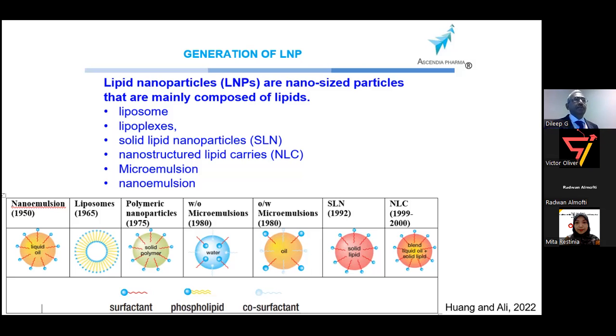Liposome was first developed by Bangham, published in Nature. You can see there's a bilayer structure. If you take phospholipids, put them in water, and emulsify, you can mix by sonication and it forms a bilayer structure. You put the drug in, it goes in the bilayer, encapsulated in the liposomes, right? It's very simple. You can extrude it, you can size it, and there are many ways we can make smaller particles, from MLVs to SUVs, small unilamellar vesicles.